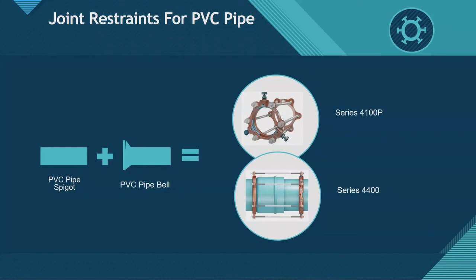For larger size, you need to use what's called a 4400 for us, but other people call it different names. And what it is, when you get to the larger size PVC, you can't just use your standard PVC restraint with a backup ring on the other side, because these bolt holes, there we are, now we're in frame, these bolt holes may not be high enough to clear the bell on a larger diameter PVC with a thicker wall. So if it's a DR14 24 inch, that bolt hole may not be out far enough to clear over the bell.